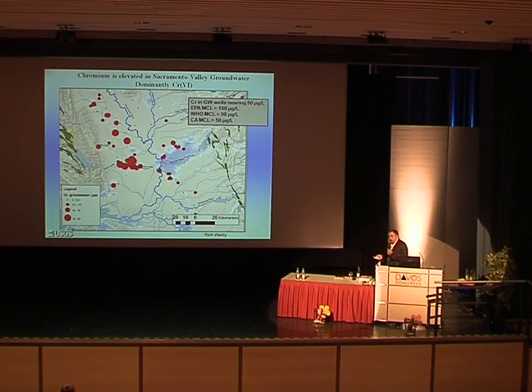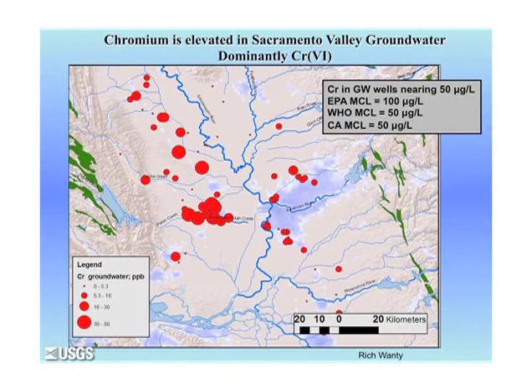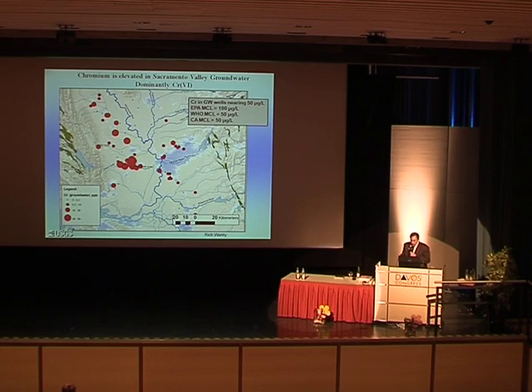Either because we've removed these magnetite rims during transport, or because of decreasing grain size of the chromite as it moves towards the valley, what happens is there's a lot of dissolved chromium in the groundwater. Chromium is most soluble in its six valent form as chromate, so this is potentially toxic chromium. The largest dot here is 30 to 50 ppb of chromium in solution. The World Health Organization maximum contaminant level is 50, as is the California MCL.